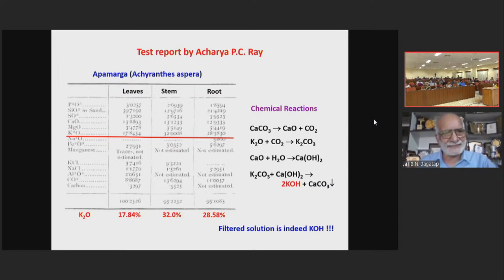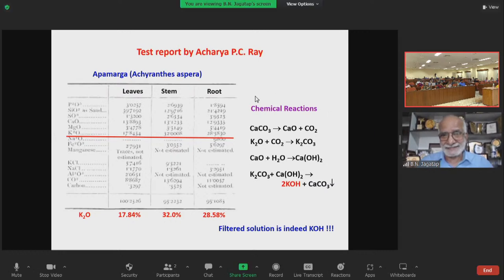Now, what Acharya Prafulla Chandra Ray does is take this plant Apamarga, takes the leaves, stem, and root, makes the ashes, and using the modern chemistry techniques of elemental analysis, he finds that the leaves contain 17.8% potassium oxide. The stem contains 32% of potassium oxide, and root contains 28% potassium oxide. Now you can see here that if the ashes have potassium oxide, then if you dissolve in water, you should get potassium hydroxide. But why this reaction?